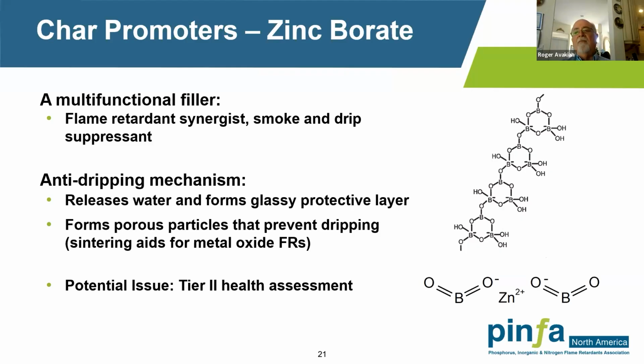You typically get a borate type of glassy protective layer, even with the zinc borate itself, but particularly in the presence of phosphorus compounds, you actually get a boron phosphorus glassy material. It's generally quite impervious to oxygen coming in, and also impervious to having, let's say, flammable combustion products or flammable decomposition products going out to burn. And it forms some porous particles that prevent dripping, probably because of higher surface area, helping to absorb some of the melt. So it does work in a very multi-pronged approach.